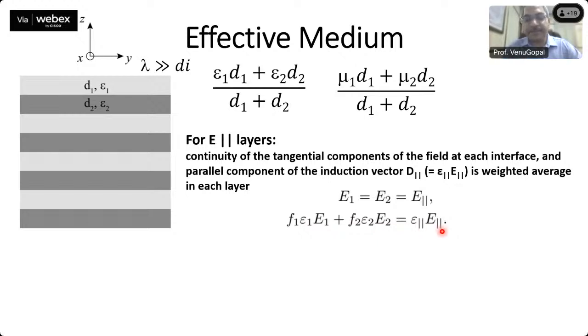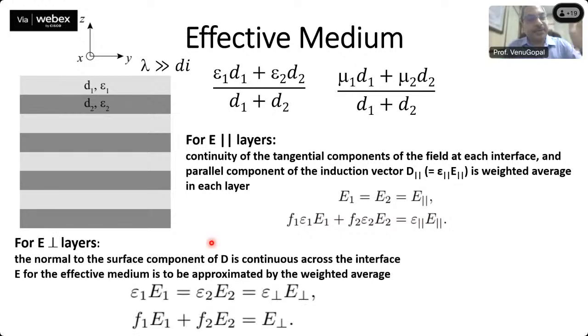Now if we have E perpendicular to the layers, then the normal to the surface component of D is continuous across the interface. And E for the effective medium is to be approximated by the weighted average, which are given here.